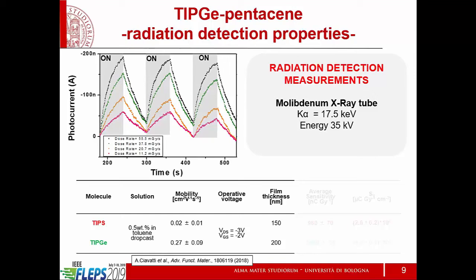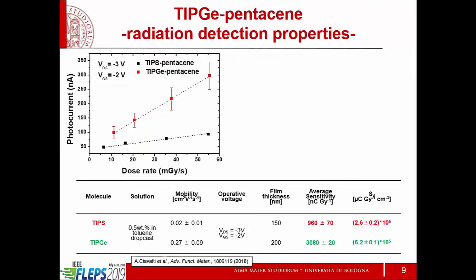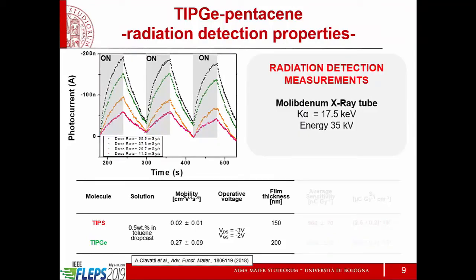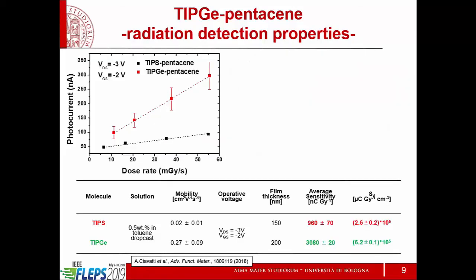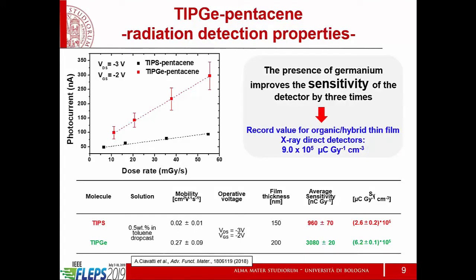Anyway, going back to what happens with TIPS germanium, you see in this graph that it responds very nicely, very similar to TIPS-pentacene, but what is interesting is that the mobility is a little higher, and that the sensitivity, which is calculated as the slope of these curves, so it is the photocurrent measured as a function of the dose rate. So one varies the dose rate, and that is why we have all these curves that we always acquire. So we change the dose rate, and then we plot the delta I over the dose rate, and the slope gives us the sensitivity. The sensitivity, you see it quite clearly, is much higher for the TIPS germanium than for the TIPS-pentacene. And you see it in numbers down here. So there is quite an interesting difference just obtained by simply changing one atom in the molecule without changing the structure of the film.